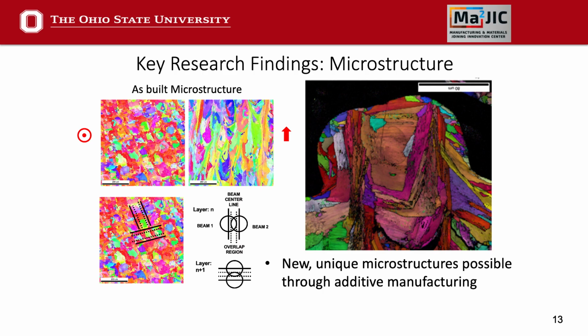Can we discuss in a little bit more detail some of the key microstructural findings along the way? Yeah, so one of the interesting things in the as-built condition of these alloys, a lot of AM materials experience a directionally solidified microstructure in the as-built condition, where you see these long columnar grains parallel to the build direction. Depending on your processing conditions, you can also see, transverse to the build direction, this cuboidal lattice grain structure. And we're trying to understand what causes that during the printing process.